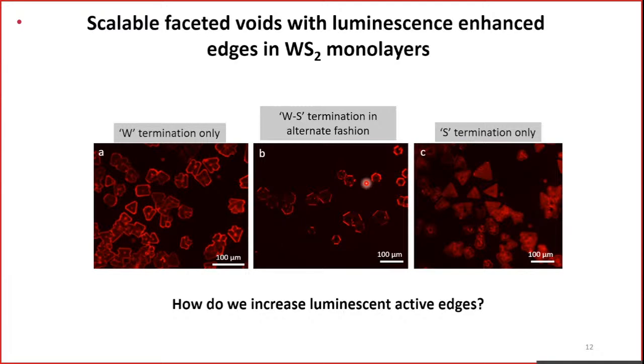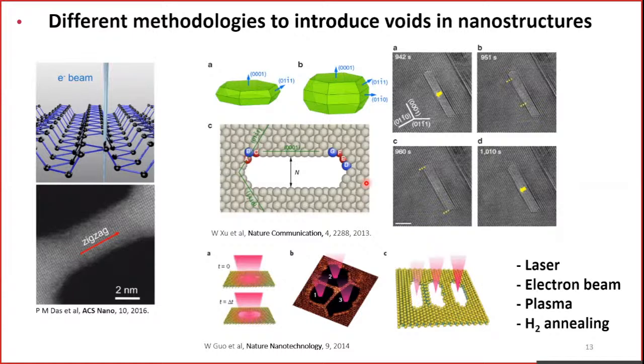When you have a tungsten termination, as I said earlier, edges are prone to attract any adsorbed species. So the oxygen can preferentially adsorb. Then oxygen can also induce p doping. Essentially, it converts some of the trions into excitons, and in some cases even produces biexcitons. That is the reason you have an enhanced emission at the interface, especially at the terminated edges.